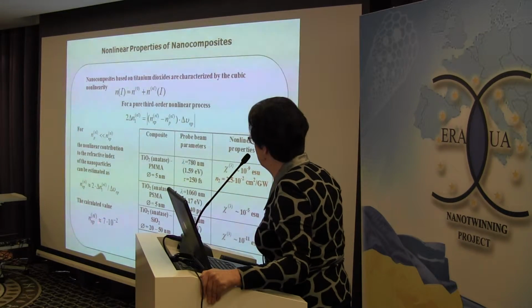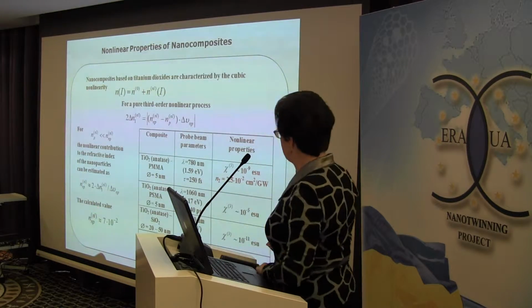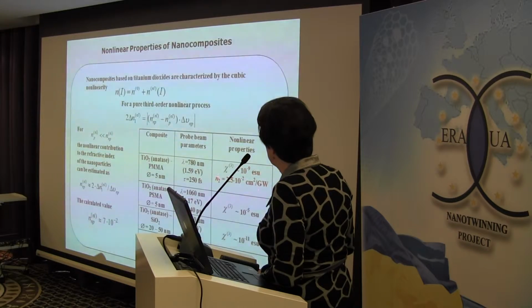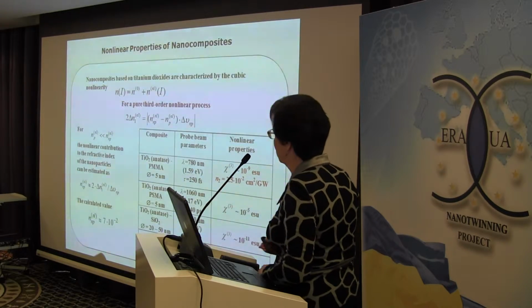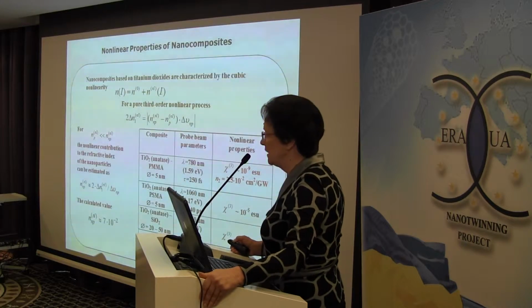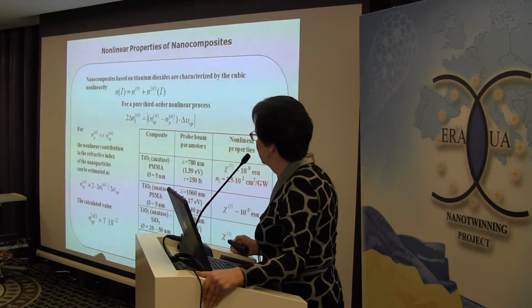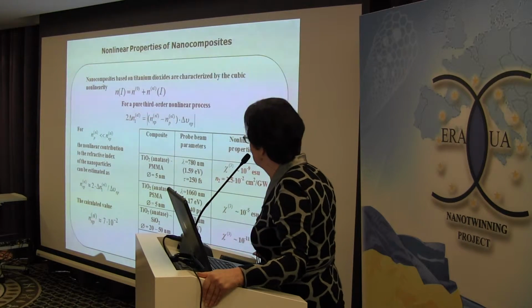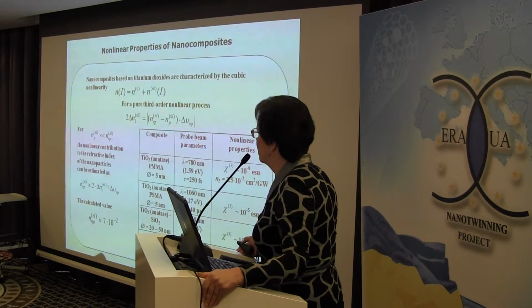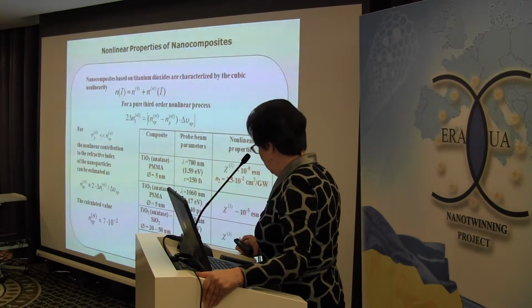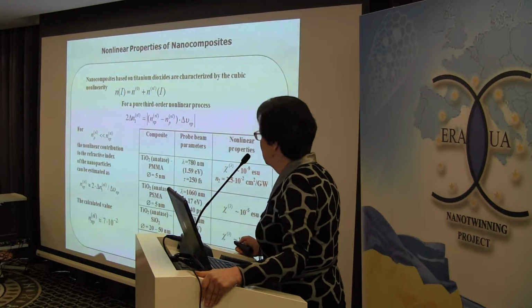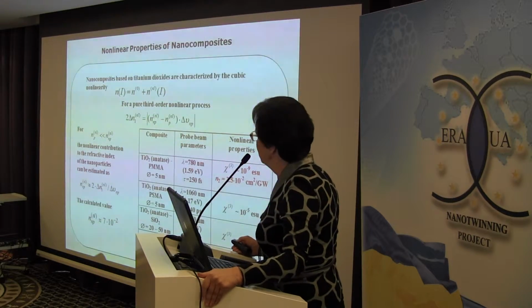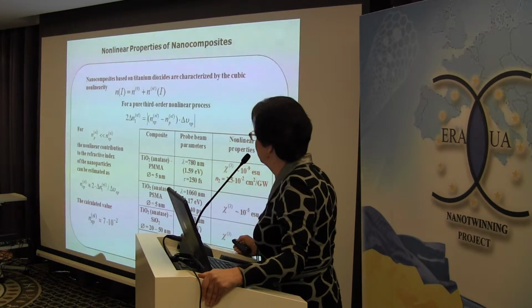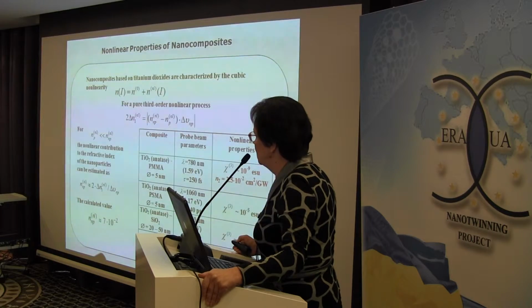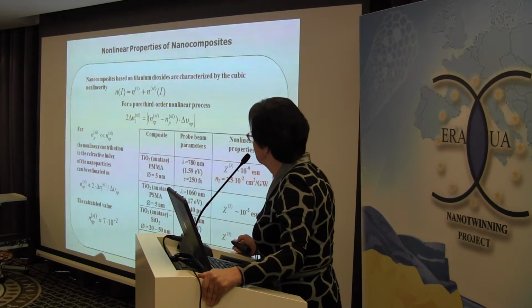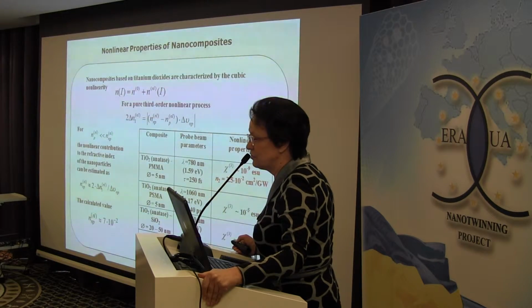The calculated value coincides by the order of magnitude with that obtained by other authors for the nanocomposite with chaotically distributed titanium dioxide nanoparticles in polymer matrix. It should be emphasized, the mechanism of the nonlinearity of this composite needs further consideration.